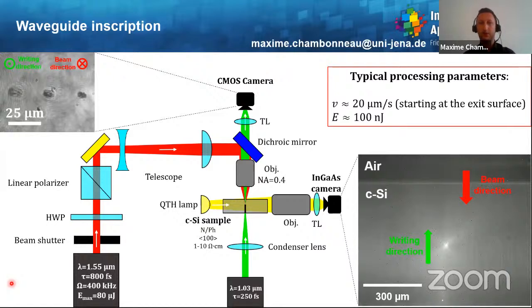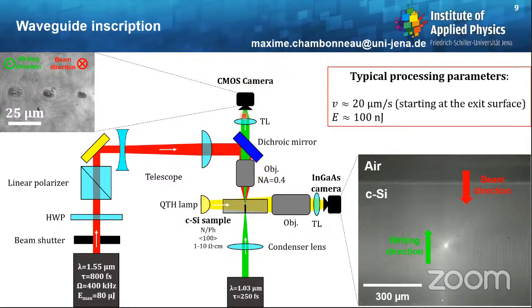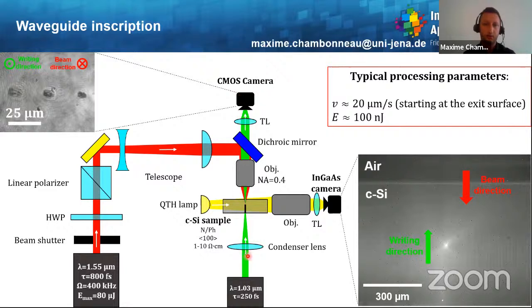So for inscribing waveguides inside silicon, we have developed the following experimental arrangement, relying on pulses at 1.55 micron wavelength, 800 femtosecond pulse duration, and a few tens of microjoule in terms of maximum input pulse energy. Then we adjust the input pulse energy by means of a half wave plate and a polarizer. So this is controlled optically. Similarly, the beam size is controlled optically by means of telescopes, Galilean telescopes in that case, before the beam is focused to the wafer, the silicon sample, by means of an objective lens. This objective lens is also part of a microscope working in transmission, as shown here, relying on this light, represented in green,